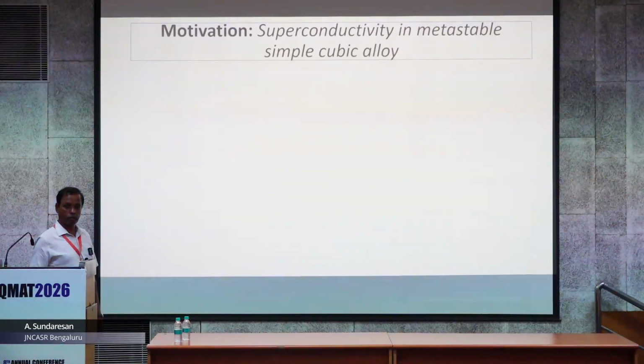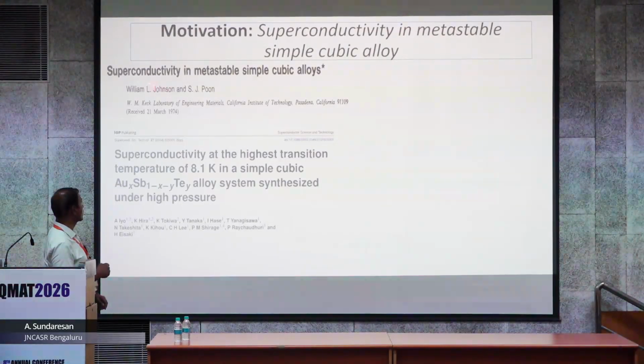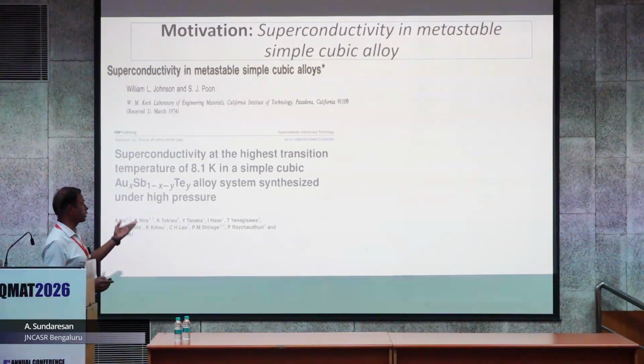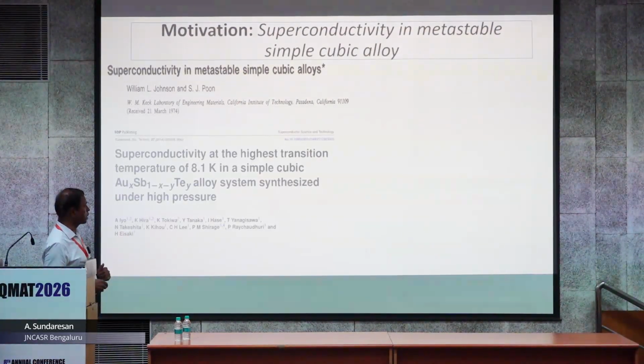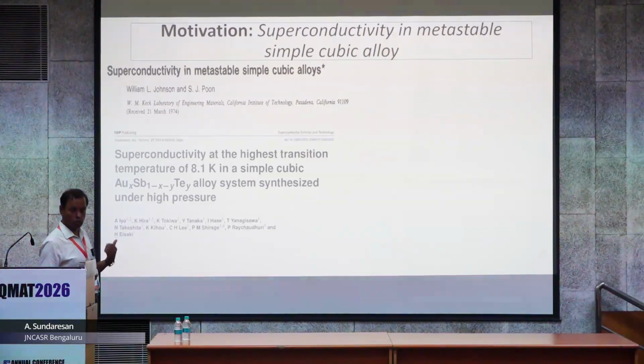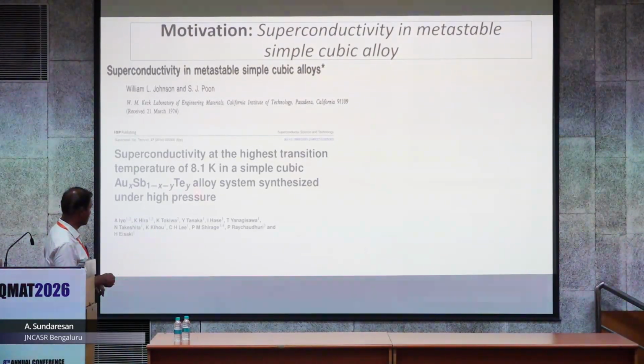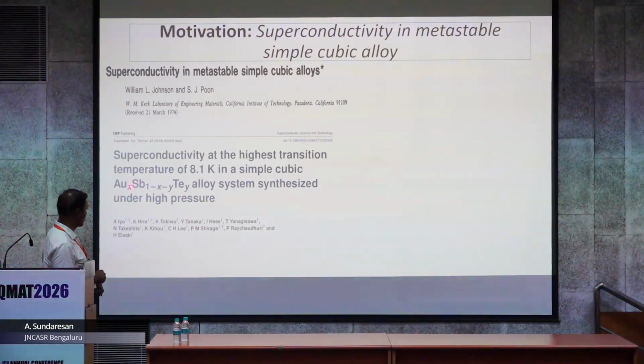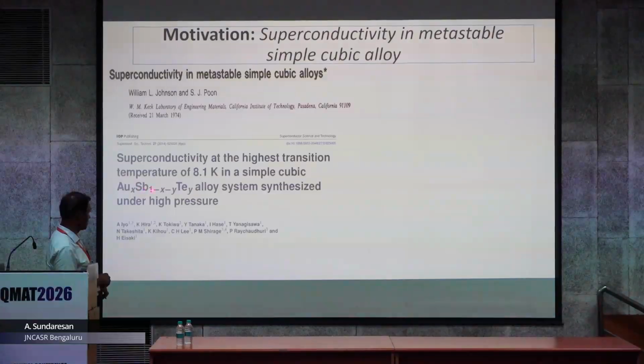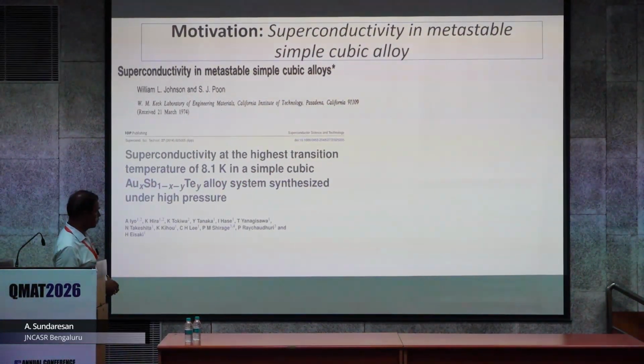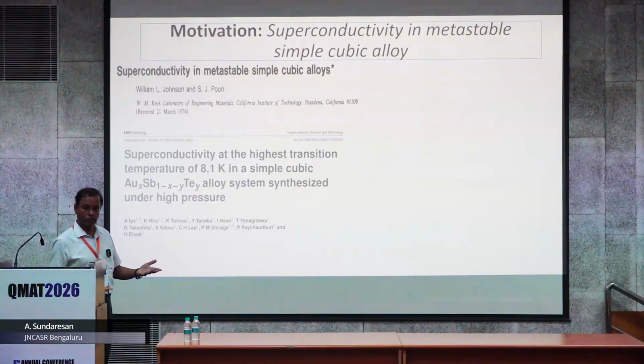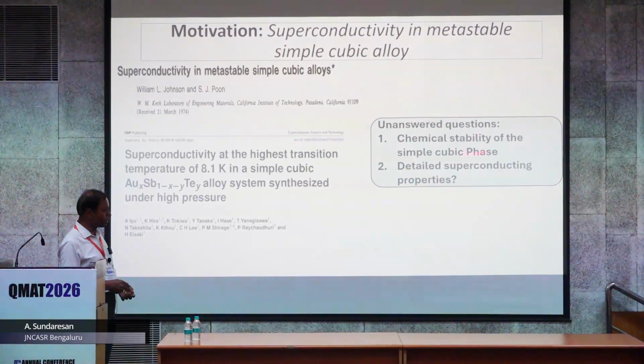As I mentioned, the other possibility for getting simple cubic is through alloys - you alloy them with chemical disorder and it's still possible to make simple cubic. There are a few papers on this superconductivity with various kinds of alloys, including gold and antimony. They studied the possibility and said there could be superconductivity, but which phase is actually responsible for it under high pressure was not clearly demonstrated until these later researchers worked on this three-elemental system and found it forms simple cubic.